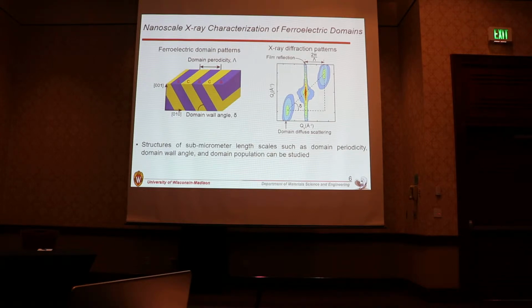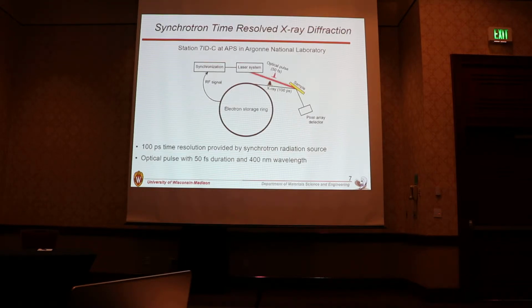But we can expect the kinetics of this transformation to occur within a few nanoseconds or even hundreds of picoseconds, so we need really good time resolution to study the kinetics. Synchrotron time-resolved X-ray diffraction provides X-ray pulses with 100 picosecond time resolution, which is quite great for kinetic studies. And station 7ID-C provides a laser system synchronized with the RF signal from the storage ring. The optical pulse and X-ray pulse spatially and temporally overlap on the sample.